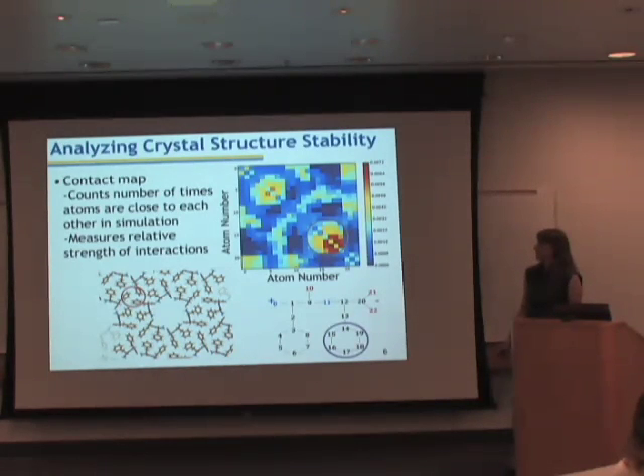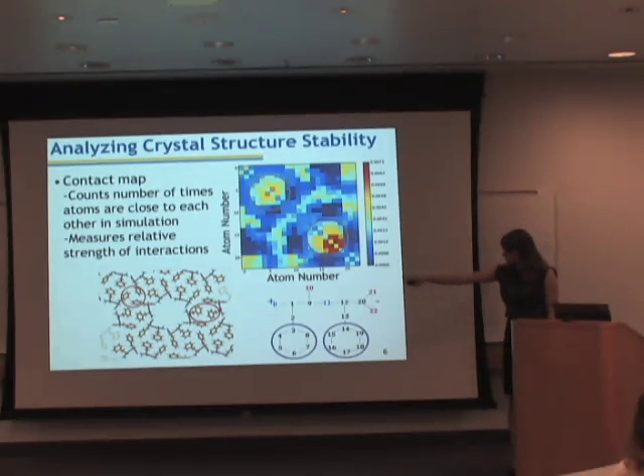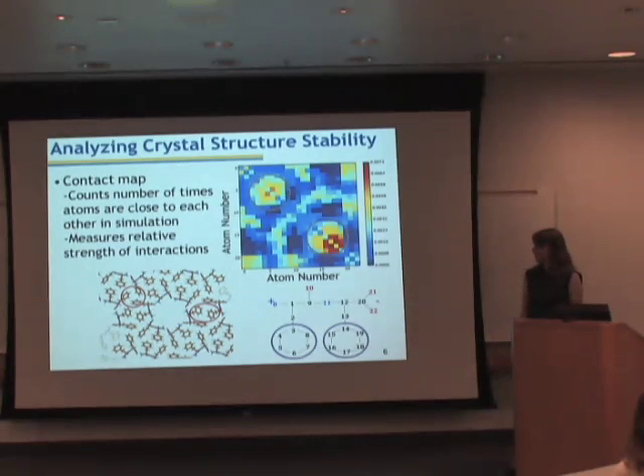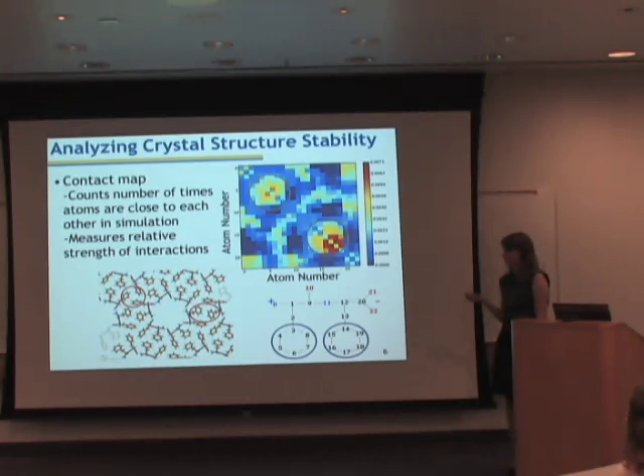We also see a high degree of interaction here on the contact map, and this corresponds to interactions between the first rings on the peptide, which correspond to groups of 2 rings coming together in the crystal structure. For this reason, we conclude that the strongest forces stabilizing the crystal structure are hydrophobic interactions rather than charged interactions.